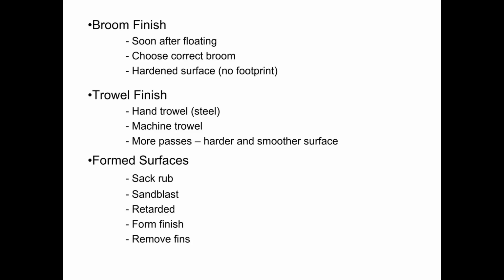So with sandblasting, we have more variety. We can do a very light sandblast that just does a light etch on the surface, or we can do a heavy sandblast that actually exposes the coarse aggregate and allows the coarse aggregate to project from the surface of the matrix. Usually with acid etching, it's just going to be a light etch just to take the shine off of the surface.